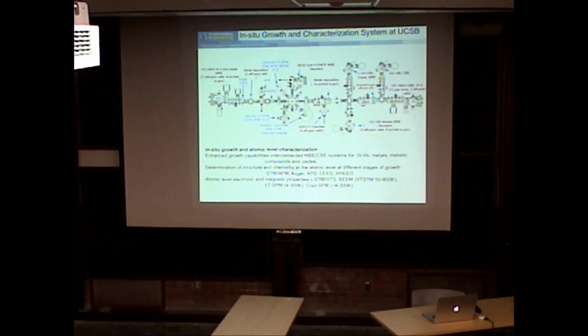Here we have now another MBE system where we grow some Heuslers. We can transfer down, we have some more depositions down here, and another chamber here. Here we have another MBE, we grow other Heuslers. Here we're growing some semiconducting Heuslers. Here's magnetic Heuslers. We can grow oxides over here, or nitrides, we're doing a little bit of work. And down here we're using chemical beam epitaxy to grow arsenide and phosphide compound semiconductors. But basically you can transfer the sample back and forth. We try to go from the clean systems to the dirtier systems, and not back again without cleaning.